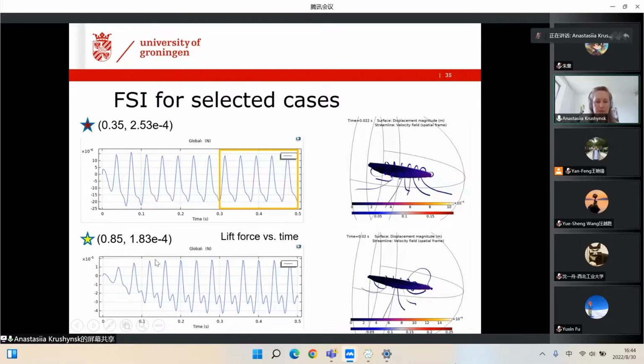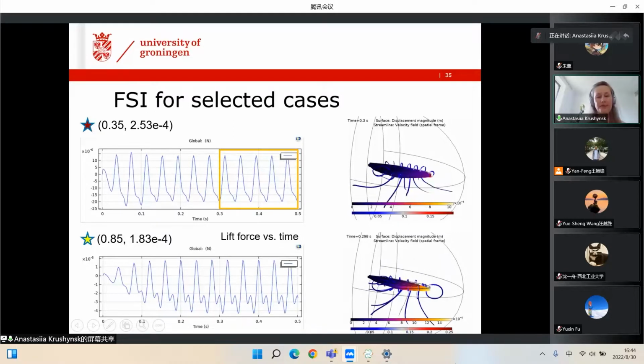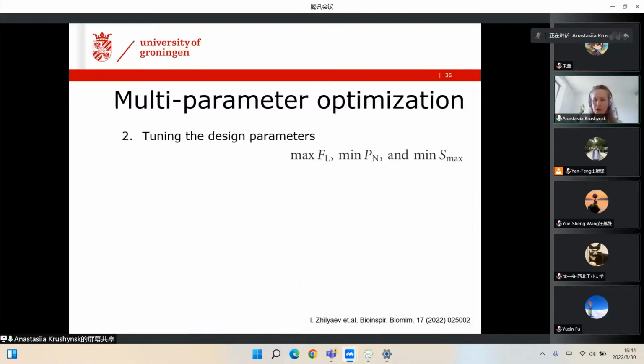The difference in amplitude is not very large, but what we see for the resonant type condition is that there appears an additional peak in the pressure distribution, which is also observed for natural insects which fly close to the resonant conditions. So we can reproduce this additional peak, and we were quite happy with that. So now, after having solved the first multi-parameter optimization step, we want really to tune the design parameters to maximize our lift and to minimize sound and stresses.